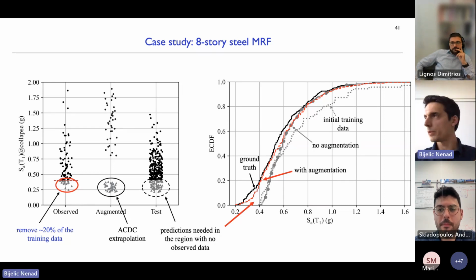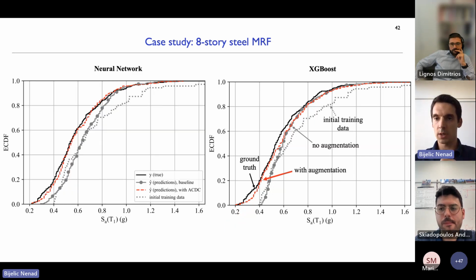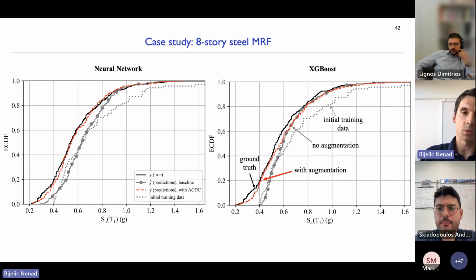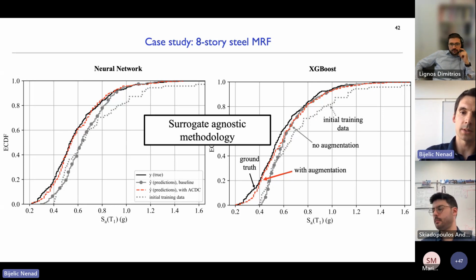But one other factor I want to leave you with is that we've done this with XGBoost on the right, but we also tested a neural network, which is a completely different surrogate, and you can see an equal level of performance. So pretty cool. The idea being that this is a surrogate-agnostic methodology. It doesn't matter if it's a neural network or XGBoost. You use what you really like.